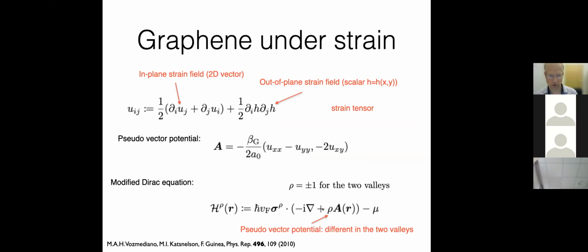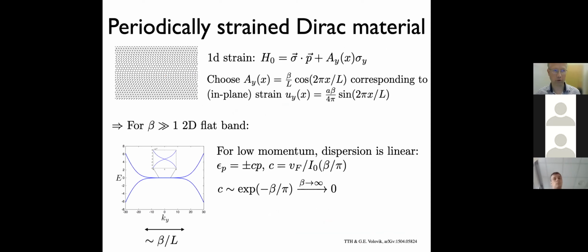This shows up in the Dirac equation by modifying it basically in the same way as an ordinary vector potential, but in such a way that the sign of this vector potential is opposite in the two valleys. So this pseudo vector potential does not break time reversal symmetry like the regular one would. What we have considered is a case where such a strain has a 1D oscillation with some amplitude beta. For example, the strain in the y direction depends on x in a periodic fashion. The strain field is basically this one, this is the pseudo vector potential, and the amplitude is indeed this beta.